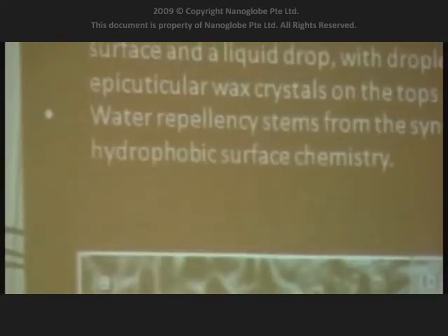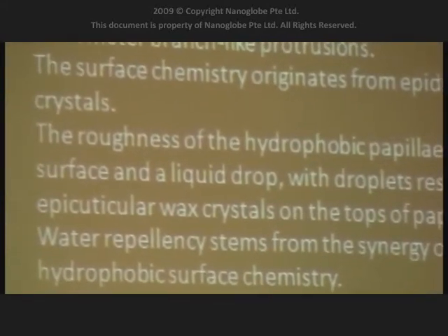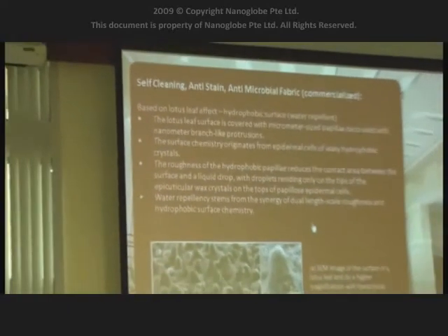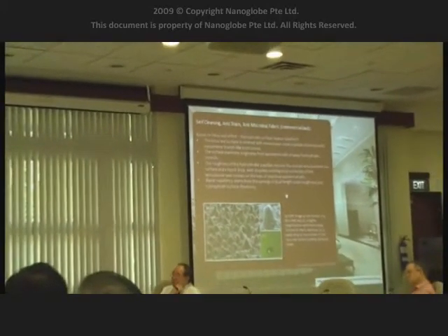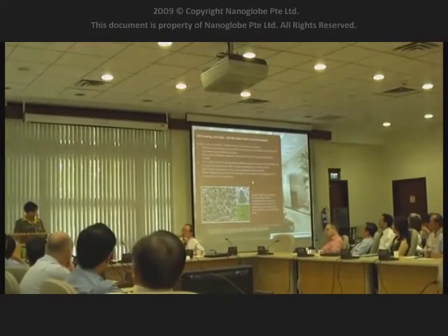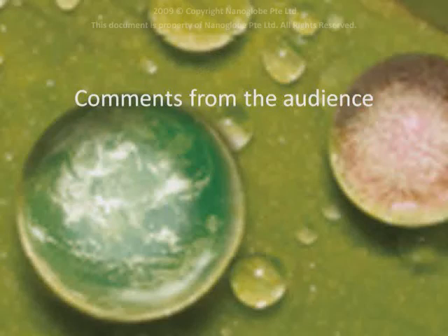Okay, so the bumps is able to hold a water droplet, and so the fact that the water droplet doesn't wet your surface, or any other material wet your surface, is that it's a combination of the effect of the length scale roughness. If I want to explain it more technically, it is that the contact angle of the droplet is larger than the critical angle when the droplet gets flat.